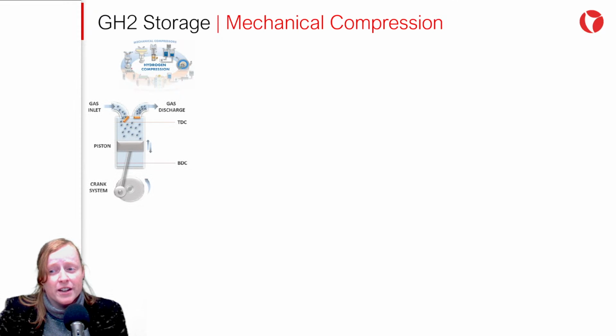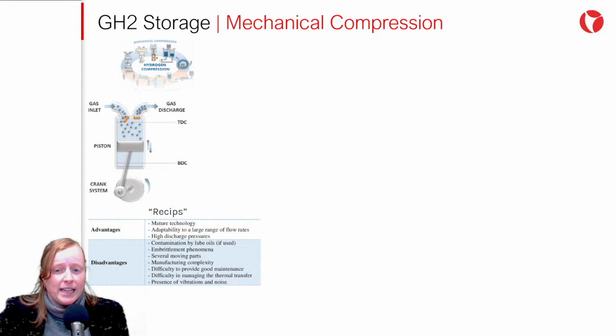Reciprocating compressors use a motor with a linear drive to move a piston back and forth. This movement compresses the hydrogen by reducing the volume it occupies. Reciprocating compressors are generally used for applications that require a very high compression ratio. It's a mature technology that adapts to different flow rates and has a high discharge pressure. Some of its disadvantages include the risk of hydrogen contamination by lubricating oils, the risk of metal embrittlement, and the